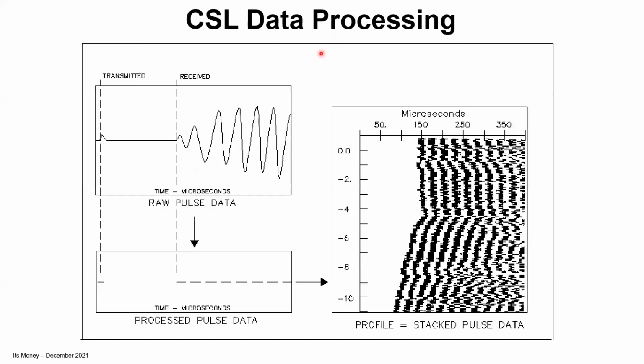But the test is performed in this manner, the point of transmission, the point of reception. So again, the time is what we're concerned about mostly. We get this waveform where the wave is received like a chirp. But if you're on a deep foundation and you're testing every 2 inches, you're going to get 500 or 600 of these chirps. So you want a way to present them where you can graphically put them on a sheet of paper and understand them.